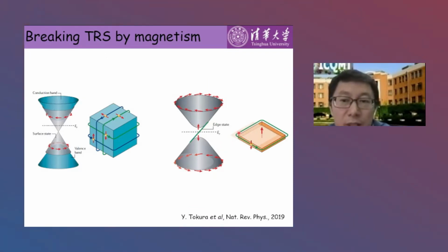On the other hand, already from the very beginning of the study of topological insulators, researchers have realized that intriguing quantum phenomena and new states can be induced if the crucial time reversal symmetry is broken. An exchange gap can be caused in the topological surface state, realizing the so-called magnetic topological insulator. In this situation, a chiral edge mode can emerge with quantized conductivity if the Fermi level is tuned in the exchange gap.